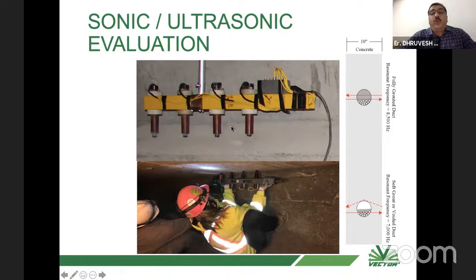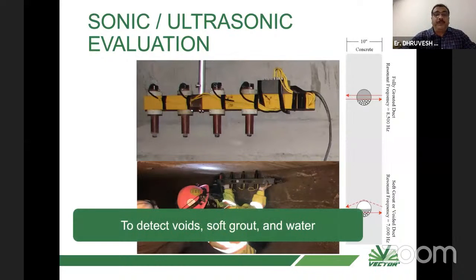So first you need to locate the tendons, and then you can use this impact echo sonic ultrasonic evaluation method. Like you can have 1 kilometer of total tendons, and you can evaluate them with a localized step-up method, to find the positions where the voids are there in the PT strand. You can use this type of impact echo sonic ultrasonic evaluation. This will definitely give you voids, soft grouts, and water if at all it is there.